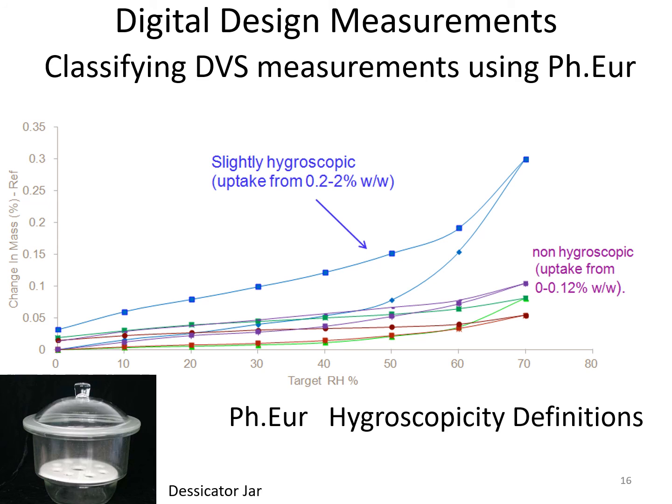This is an example of where we're measuring the dynamic vapor sorption of the material. Here we're changing the humidity, so it's 0% at the bottom and 80% on the far side. And up the y-axis, you've got the change in weight. You can do this either with a sophisticated machine called a DVS measurement machine, or you can simply do it with a desiccator jar with saturated solutions of salts at the bottom, and then you put the powder in, weigh it before you put it in, and weigh it again afterwards to see how much moisture it's picked up. And these solutions will have different humidities.